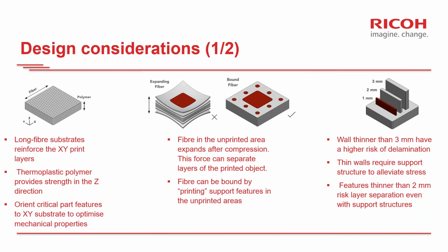So this risk of delamination also has an impact on the minimum features that can be printed with the technology. As a rule of thumb, areas with a wall thickness below 3 millimeters will have a higher risk of delamination. This can be overcome by adding those support structures to alleviate stress in those areas and reduce the risk of delamination. And for areas that are thinner than 2 millimeters, there is still a risk of delamination even with support structures.